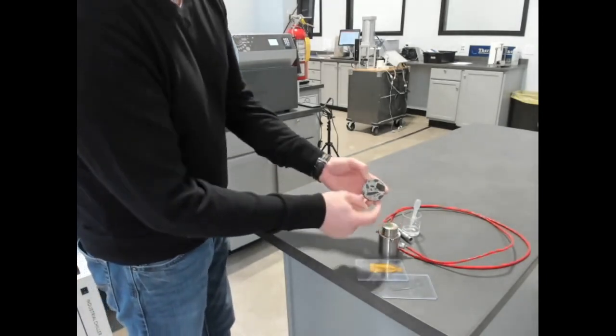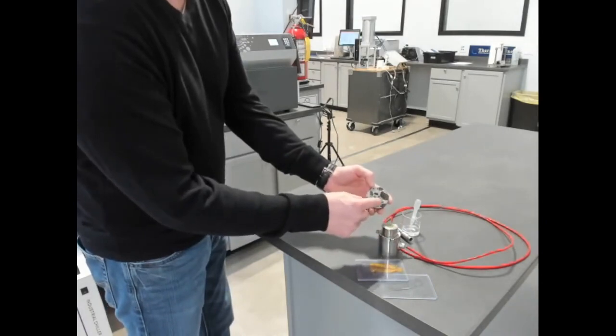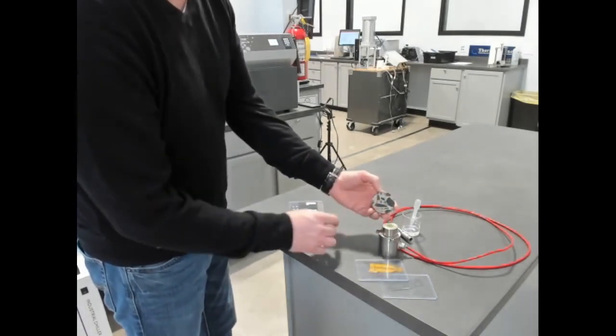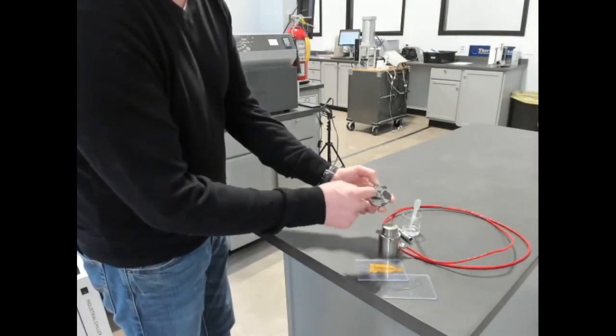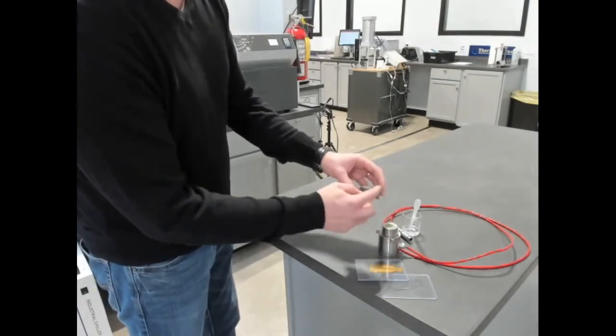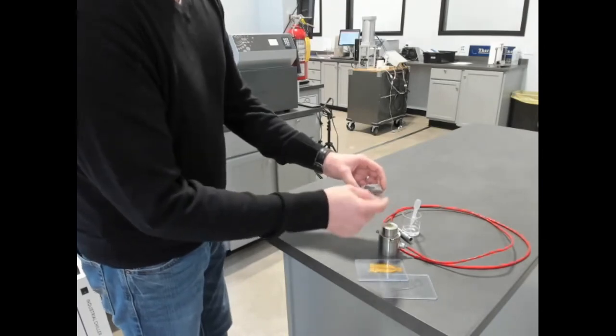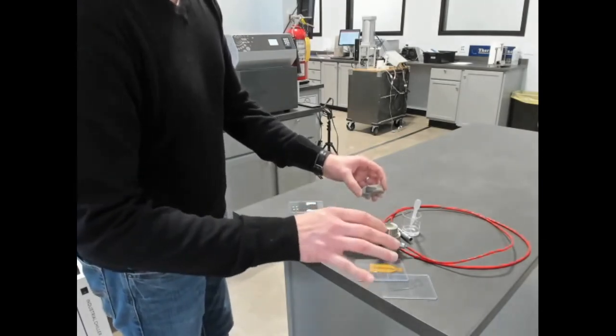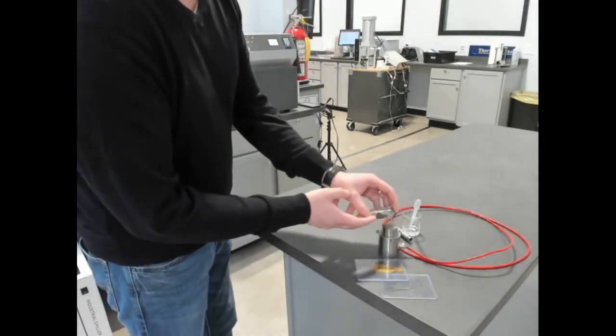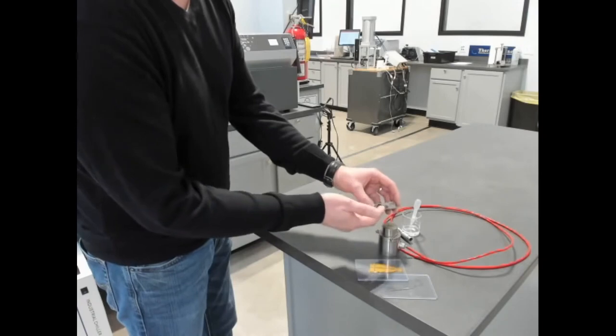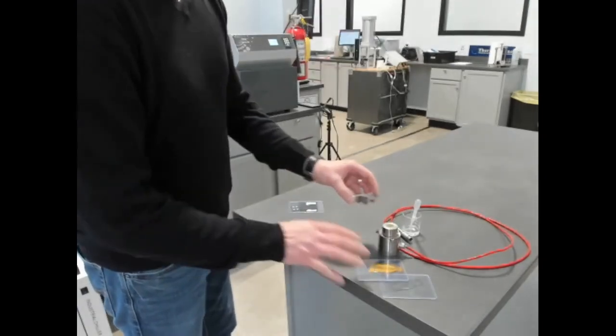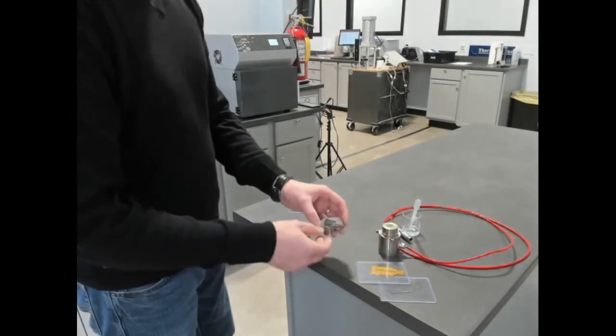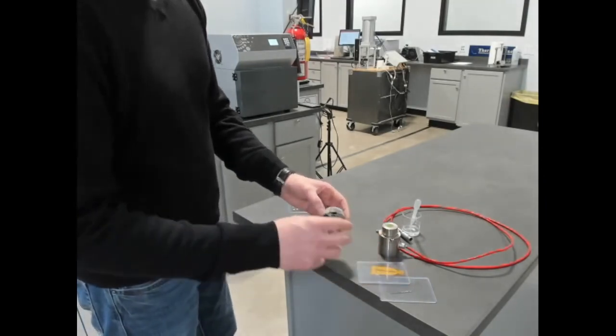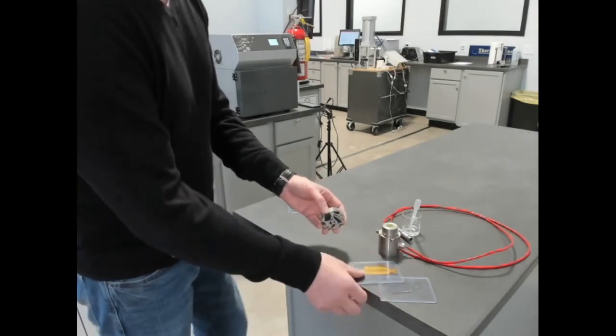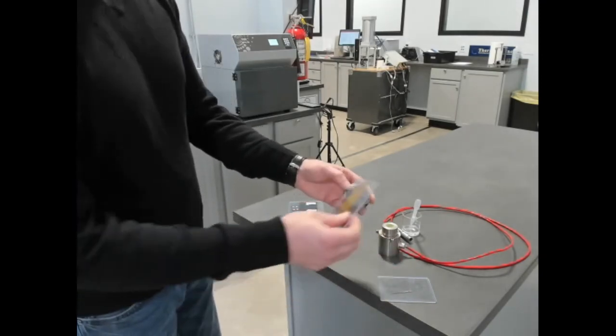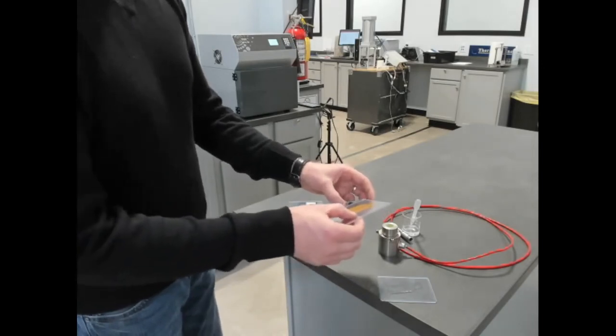What's the issue there is even when you take 13 millimeter diameter circles and place them at different locations, you can see that that value is never going to be truly representative. And then you look at the cross section. The cross section is also heterogeneous. So the one advantage you have with a longer test time is that you can try to average locations by doing multiple locations, but also average the thickness by using a wide variance of time. The traditional TPS sensors have test times of 1 second to 1280 seconds. And what that means is that you can increase your averaging of the sample by penetrating deeper into the material.